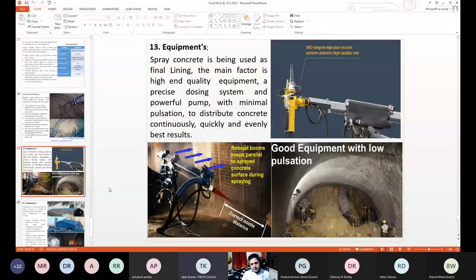You can see the machine, 360-degree rotation of the nozzle, and its distance from the surface to nozzle should be 0.5 to 1 meter, and the angle should be perpendicular to the face, and the good equipment gives you low pulsation and good results, as you can see on the screen.